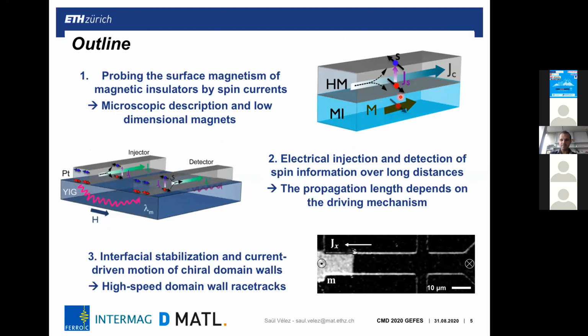In particular, we will explain how the spin transport across the interface occurs, microscopically related to the properties of the interface, and how we use this to probe the magnetization of a low-dimensional magnet that doesn't exhibit long-range ferromagnetic order. I will also show you that in non-local structures, as the one shown here, you can electrically and thermally excite magnon currents and detect them non-locally. And I will show you that the diffusion length of these magnons depends on the excitation mechanism.